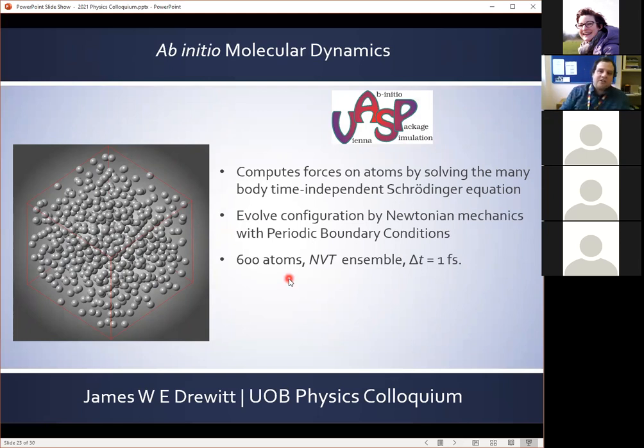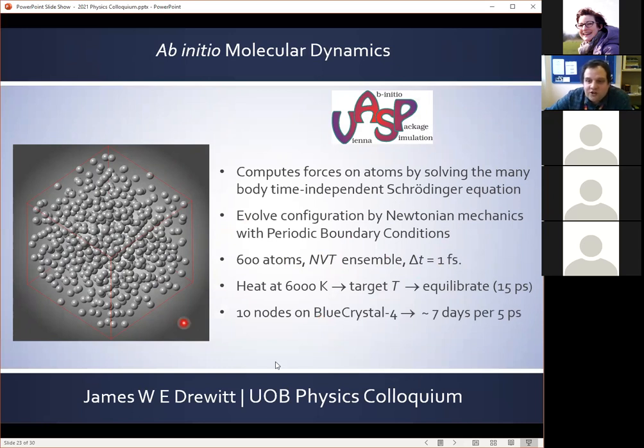In this case, I used 600 atoms in each simulation cell in order to accurately reproduce the measured structure factor. And I used the NVT ensemble, so the number of atoms, volume, and temperature remain the same during the simulation, where I heat up to 6,000 Kelvin to target temperature and then equilibrate for 15 picoseconds with a time step of 1 femtosecond. And so just to give an idea of the timescale of these simulations, using 10 nodes on BlueCrystal 4, so that's 240 CPUs, takes around 7 days for every 5 picoseconds of simulation.